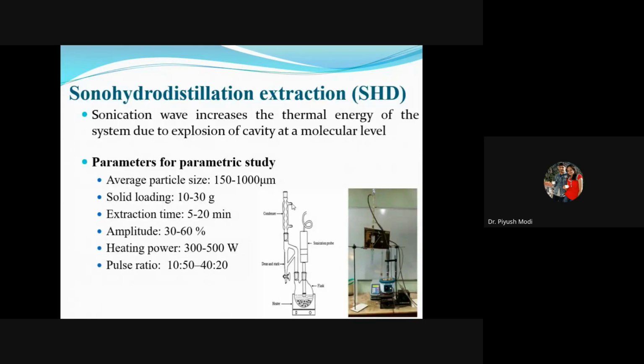Then, after that, you can see the sono-hydrodistillation extraction, SHD. The probe is placed over the flask, so it ruptures the material and ultrasonic waves are created. One of the parameters is amplitude. I studied a range of 30 to 60% amplitude, and pulse ratios of 10 seconds to 50 and 40 seconds to 20. It's an on-off cycle.